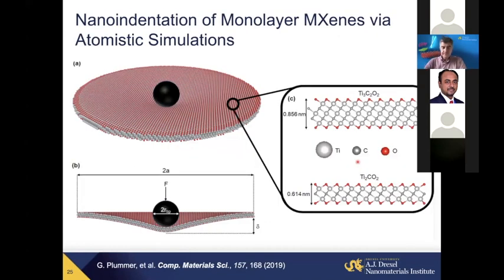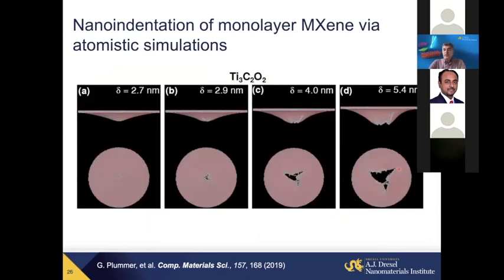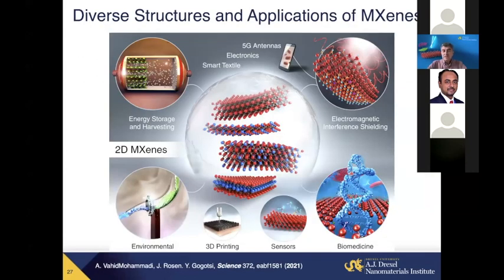And we worked with colleagues to do further simulation of deformation and failure of MXene sheets, confirming what we observed experimentally, that in fact there is a gradual failure of these materials without catastrophic cracking. So it also means that these flakes are difficult to damage. They won't break, unlike, say, carbon nanomaterials in dry environments. They keep their protecting layer terminating the surface. They don't fail easily, and that's actually one of the properties that contributed to these diverse applications.